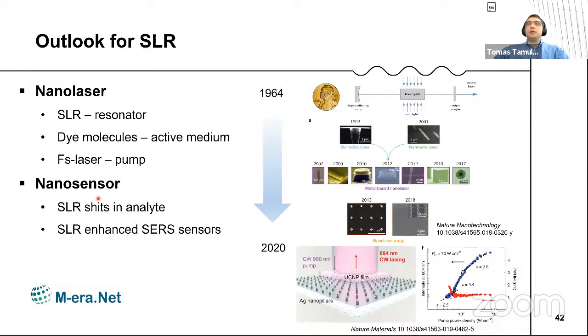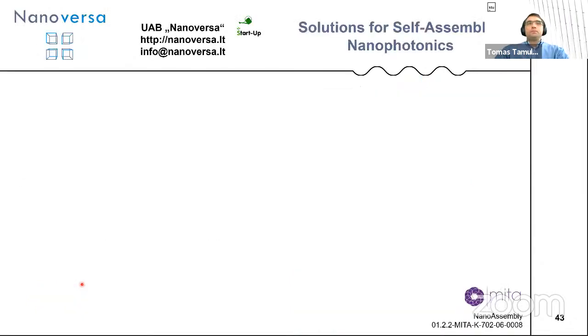The other application for the SLRs is nanosensors, and they could be very sensitive to some molecule bindings on those cubes, because they might shift the resonance and the mechanical properties. And also, there is a very nice application of SLR-enhanced SERS sensors. So you can enhance the Raman signal by having a resonant excitation from the nanoparticles. And I don't have time to speak about this, unfortunately, but we just recently got a project where we will work on those directions.